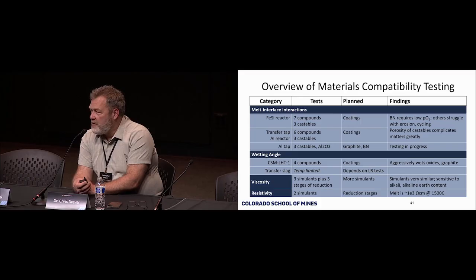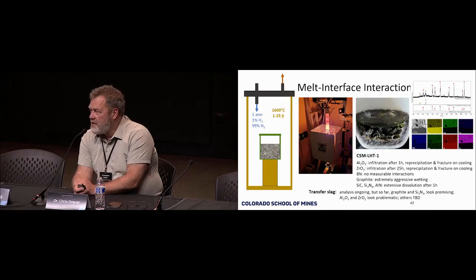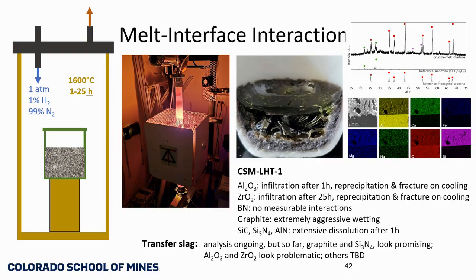We've also measured wetting angle, viscosity, and resistivity directly of various slags, molten regolith as well. This is a little bit of detail on this. These are melt interaction measurements, where a small bit of regolith simulant is melted in a crucible. We then look at the interaction of the crucible wall with the melt, and there are EDS measurements on the right that show the formation of iron within the melt at the wall, penetration of the melt into the wall, and the recrystallization. There's a lot that can be learned from this. In fact, there's another publication coming out that'll detail this.